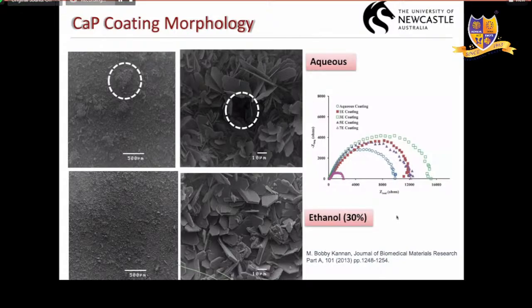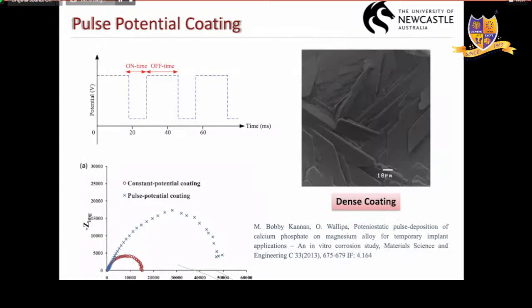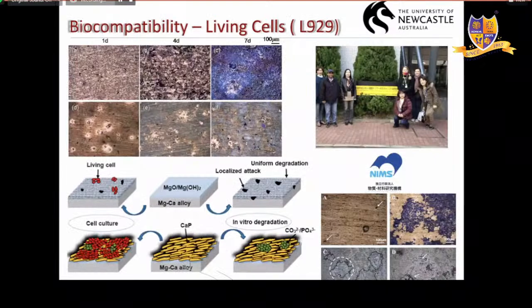Thank you. So as a next step, we further controlled the conductivity of the electrolyte and the kinetics by using ethanol and a technique called pulse potential, and we created a very flat, dense coating. It is one of the highly resistant coatings. We did some biocompatibility testing on those coatings. I visited NIMS, an institute in Japan, and we did the biocompatibility testing there. These coatings have produced quite good biocompatibility, which is good news.